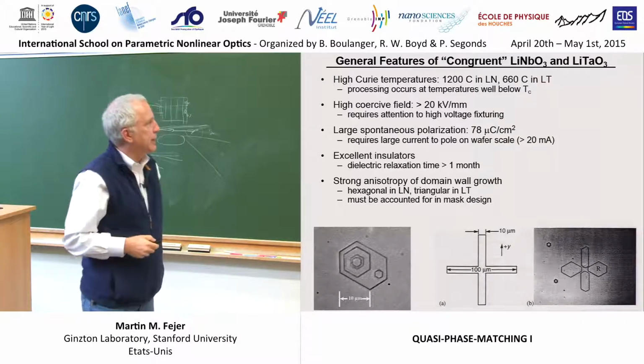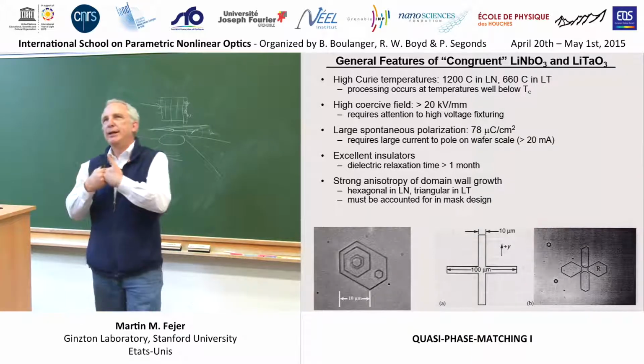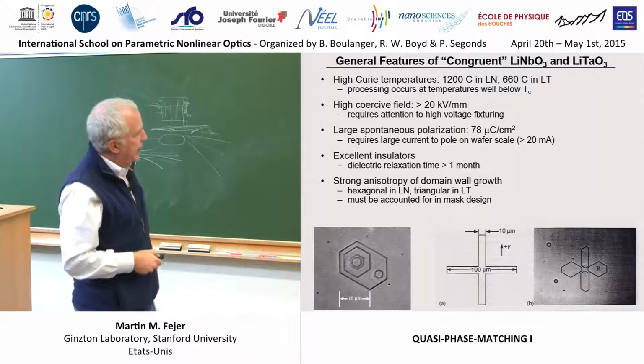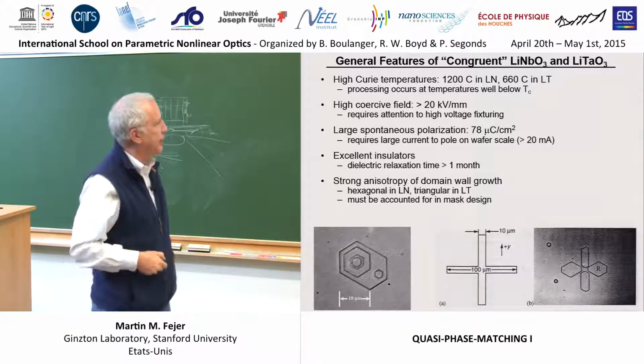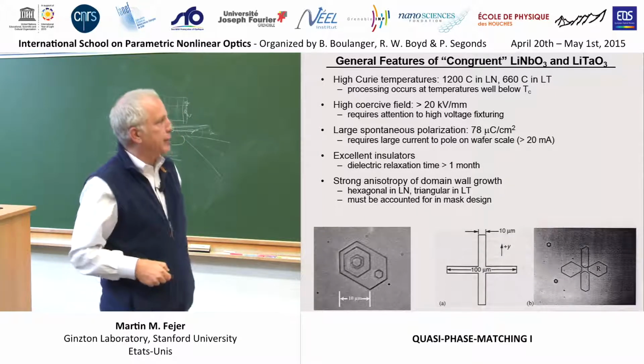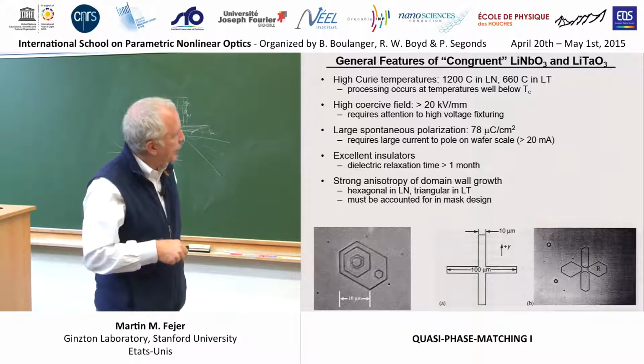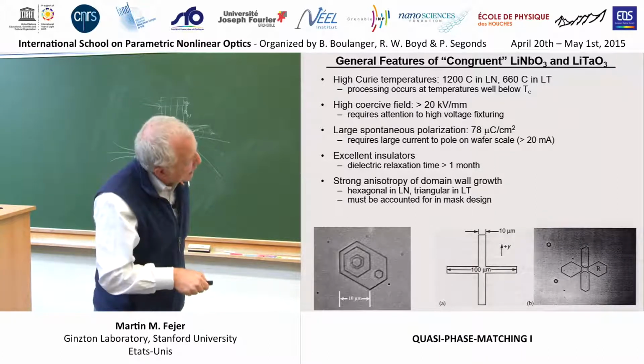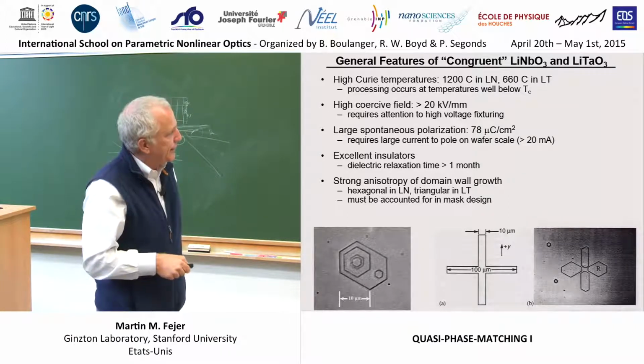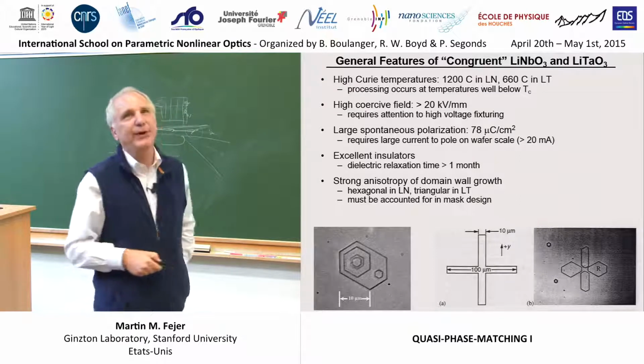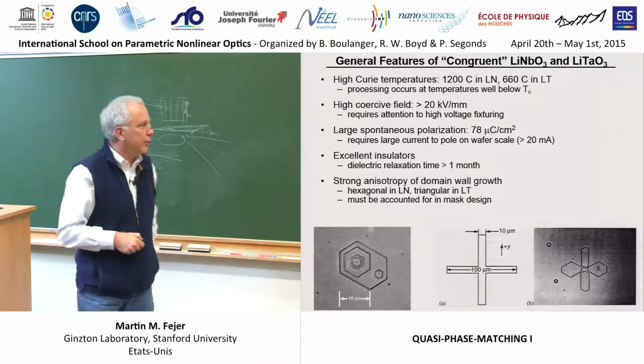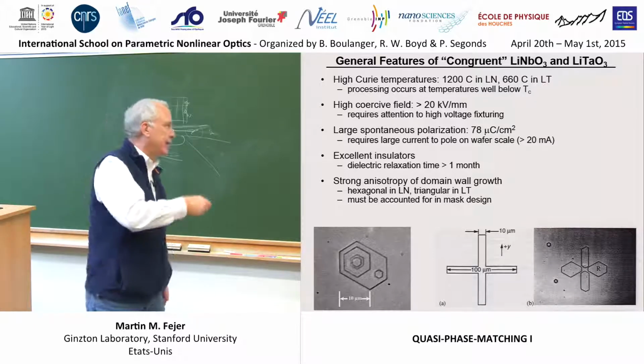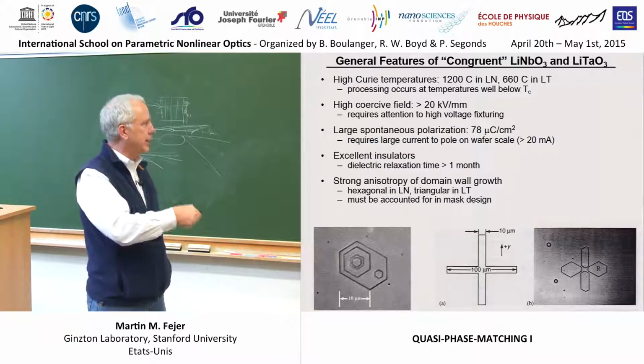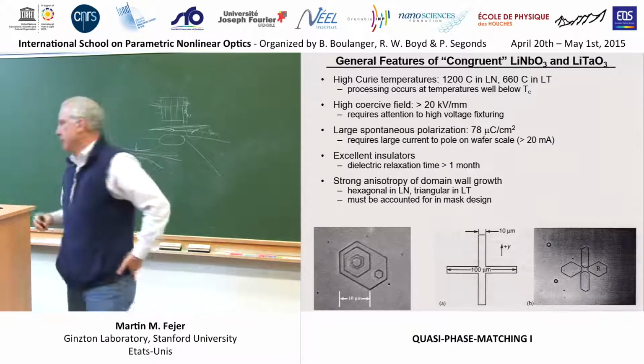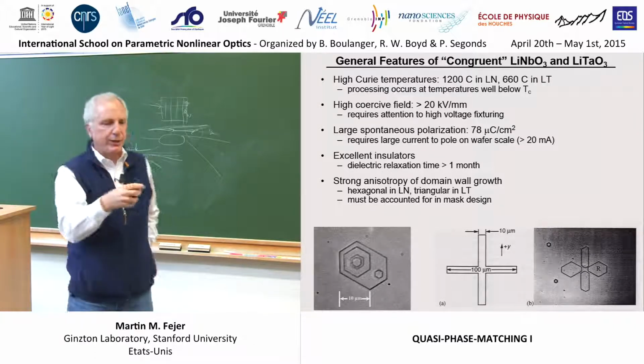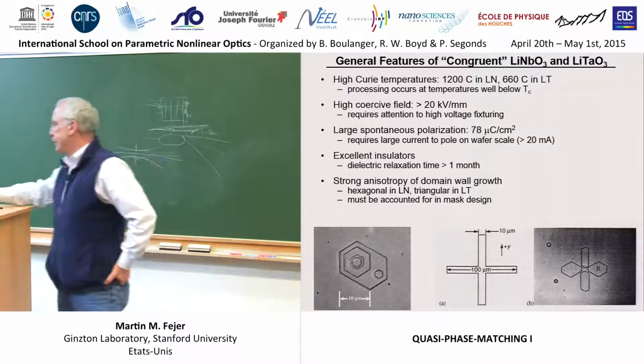Like I said, they're excellent insulators, and the energy of a domain wall is not independent of its orientation. They have 6 preferred directions related to the crystallographic axes. If you apply an electrode and try to pole this material, if the sides of your electrode line up with one of these desirable directions, you get a nice straight domain. If you are not along a good direction, well, the domains are going to find their preferred direction and not listen to you anyway. So you have to choose the orientation of the grating so that the preferred direction of a domain wall lies along the direction that you're trying to make your pattern. There's a 3-fold axis in this material, and it turns out to produce a 6-fold symmetry in the preferred directions.